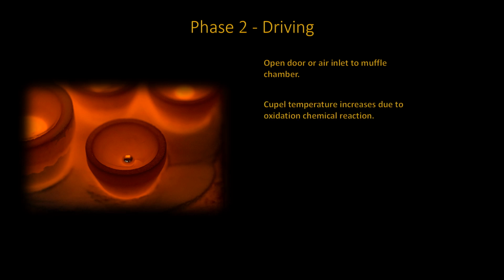Once the uncovering of the lead bead is completed, which should be about 10 minutes, the muffle door should be opened, or the air inlets of the muffle chamber unsealed, to allow for an adequate air supply. The oxidation reaction will fully begin, and the Cupel's temperature will start to rise due to the chemical reaction taking place, producing the lead oxide. The furnace temperature must be decreased to 750 degrees centigrade to compensate for the rise in Cupel temperature and maintained.